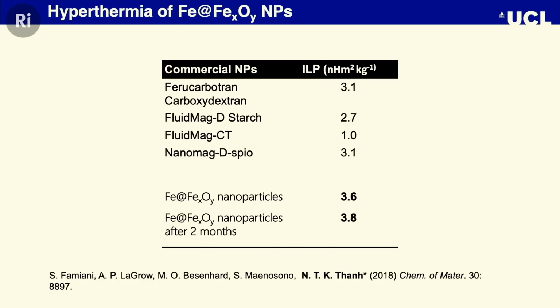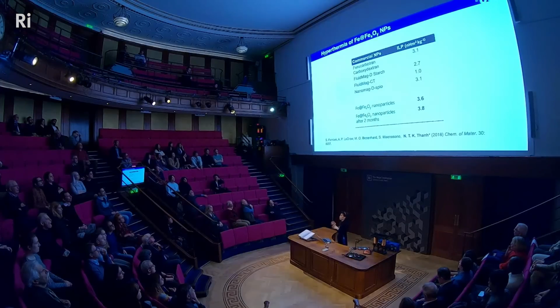So at the top of the table, that was the commercially available iron oxide nanoparticle. The value is about 3.1, and our iron oxide nanoparticle makes an improvement. We got 3.8, but then our nanoparticle is stable for 2 months. Remember what I mentioned about the stability.